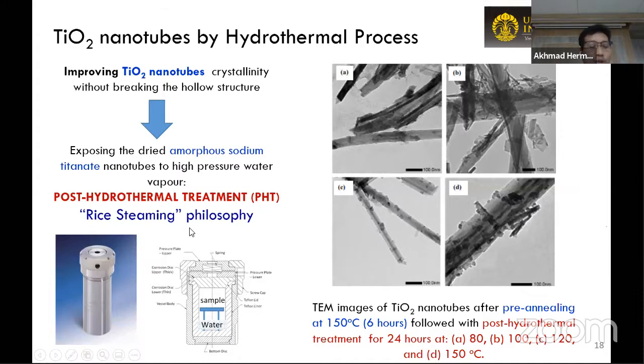Actually, this is the same as what we do every day in our life. This is the rice steaming philosophy. We use, for example, a dandang in Bahasa Indonesia to make the rice that has been boiled more well-cooked. We actually do it using the same philosophy, the rice steaming philosophy. Of course, we put our sample using a special fixture in this autoclave, and let the water vapor do its duty to improve the crystallinity of the material. So this is the TEM image of the nanotube.